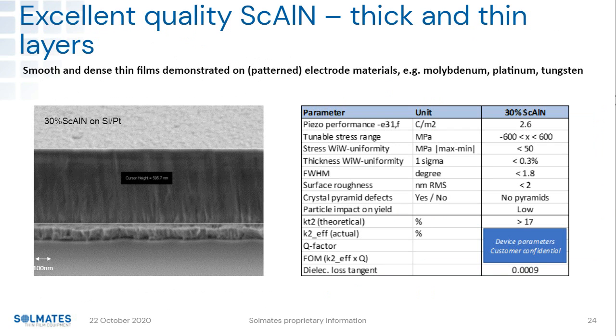So first the basics. This is for 30% scandium doped aluminium. We want to show you some basic performance numbers. So there's a good E31F. The tunable stress range, we can go from compressive to tensile over large range. Stress uniformity, 50 megapascals. And this is an important number because this is full range, right? So this is maximum minus minimum.